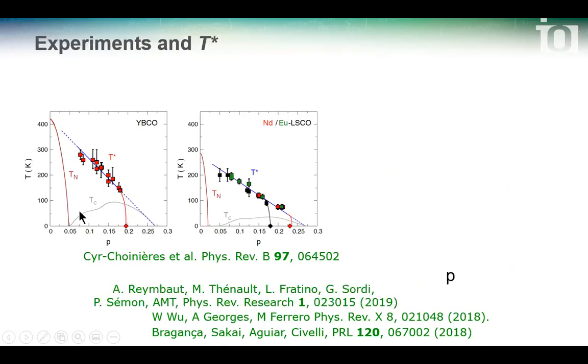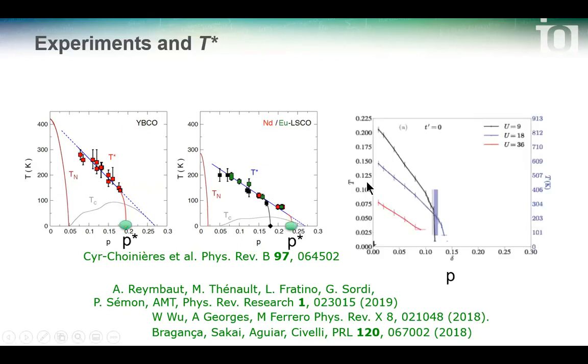And we can compare with some experiments that Louis' group did, where there is temperature and doping again for one compound, YBCO, and for another compound. And this T star is not for the spin susceptibility, it's for the resistivity, but the spin susceptibility just starts a little bit earlier. And this is what we get. As a function of U, you see that U equals 9 is this black curve. If you go to U equals 36 it is this red curve. So it goes down when you increase U. And here you see that it goes down also when the Néel temperature goes down.